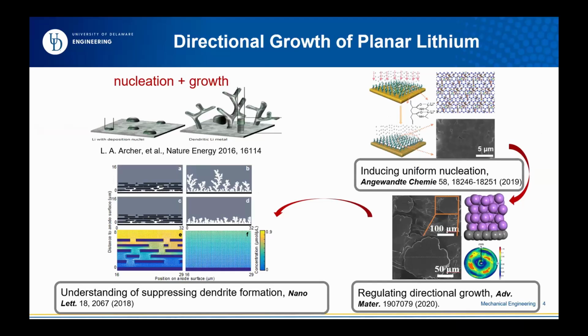The third part is about batteries. We know we try to avoid this disaster, which typically happens in lithium-ion batteries and probably becomes more pronounced if you try to develop lithium metal batteries. We first try to understand that dendrite formation is pretty much the primary cause of short circuits inside batteries. We try to understand step by step, starting with nucleation, and try to avoid this dendrite formation.